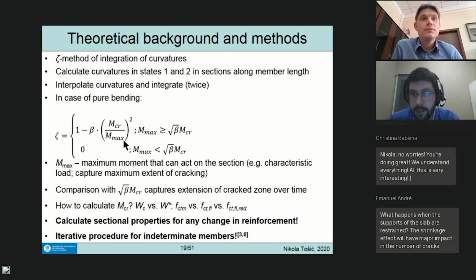Why? Because Zeta models the extent of cracking, and the characteristic load will appear at one time during the life of the structure. Once it appears, it's going to crack the structure more than the quasi-permanent load. But those cracks remain even after the characteristic load is lifted and you're only left with the quasi-permanent load. So in order to model that fact and bring you closer to state 2, here you always plug in the maximum moment that can ever appear on your cross-section.